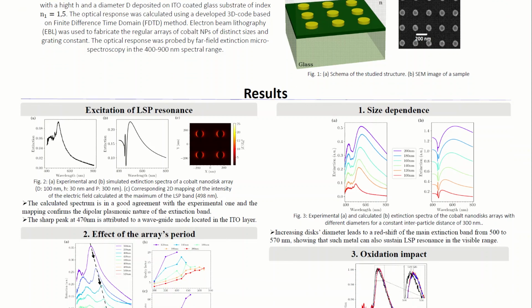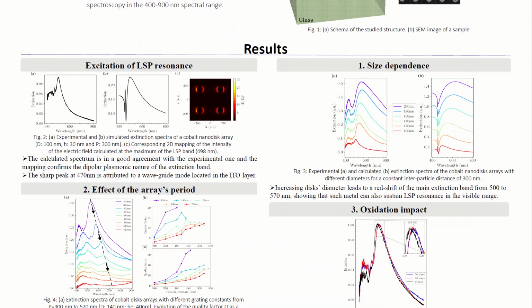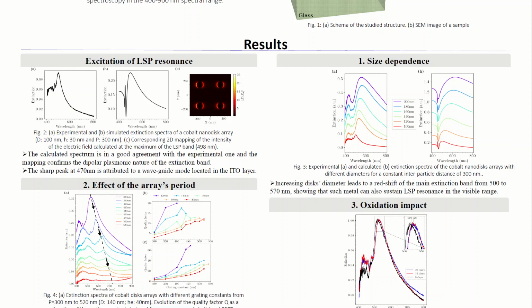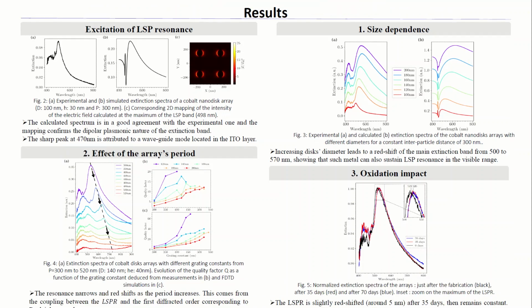Since electron beam lithography allows the tuning of morphological parameters, we investigated the impact on resonance when modifying the diameters. As expected, the resonance seems to redshift when increasing the diameter of the nanoparticles. The observed resonance is found to be broad due to the very lossy metallic nature of cobalt.